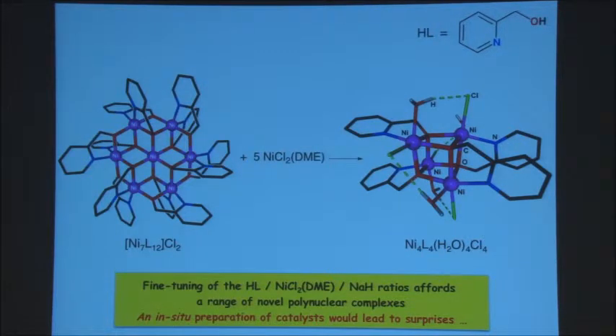So if you're not careful, you think you have one structure in your bottle, but eventually under reaction conditions, you may convert it into another one, which might be more active or less active, display different magnetic properties. So the fine-tuning of the metal, ligand, and base ratios is very important. And you have here a huge diversity of options. Again, if you were doing in situ catalysis, you would miss all that. You would have no idea of what you have in your reaction mixture. So no way you can assign a property to a given molecule. And that, I think, would be very frustrating.